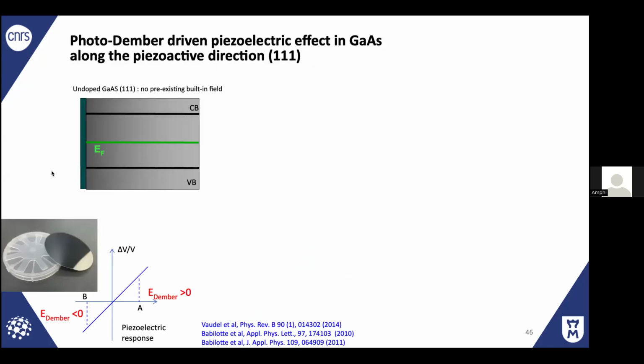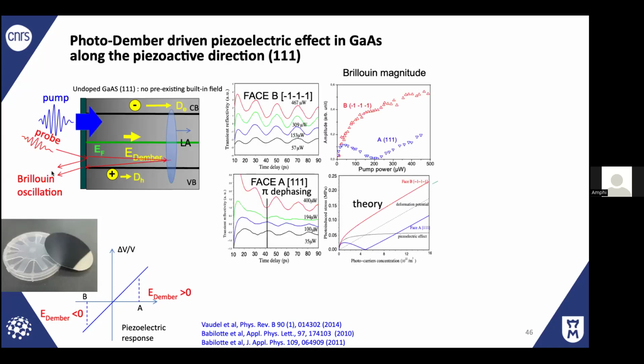We did such an experiment. We shine light, creating the Dember field, and we probe by Brillouin as well. We look at how this Brillouin signal changes as a function of the pump power. This is a low power, and as we increase it we see the oscillation amplitude increasing. When you plot it, it looks like that, the red part. But if you do the same thing for face A, you see the oscillation increase, and after a given power the amplitude nearly vanishes, and then it increases again after that. But there is a phase dephasing that occurs. And if you plot just the amplitude, you have things like that.